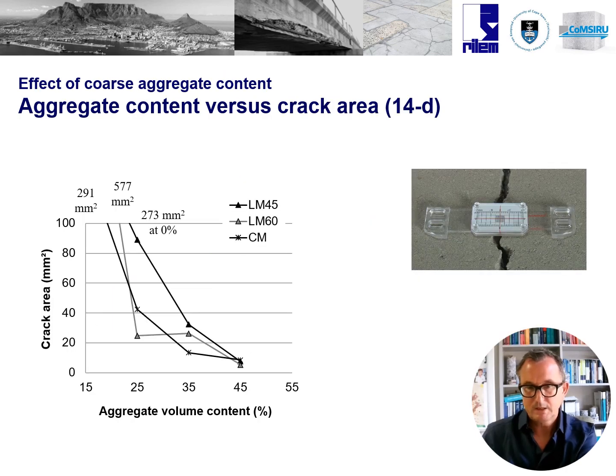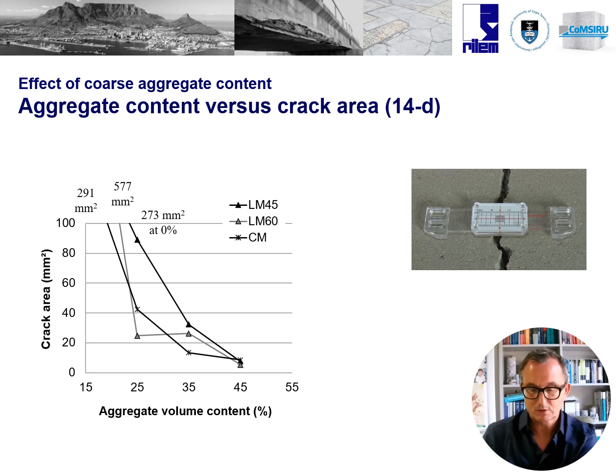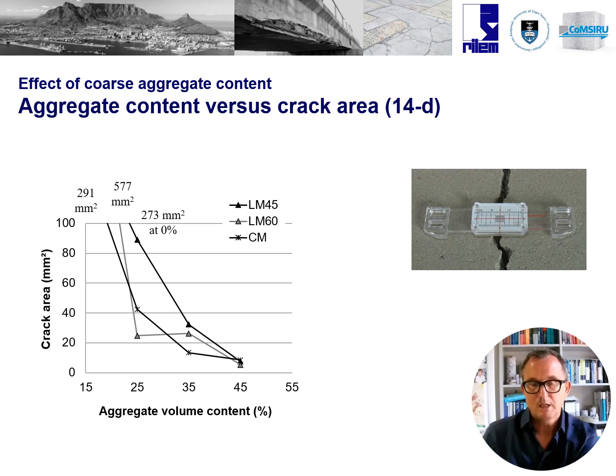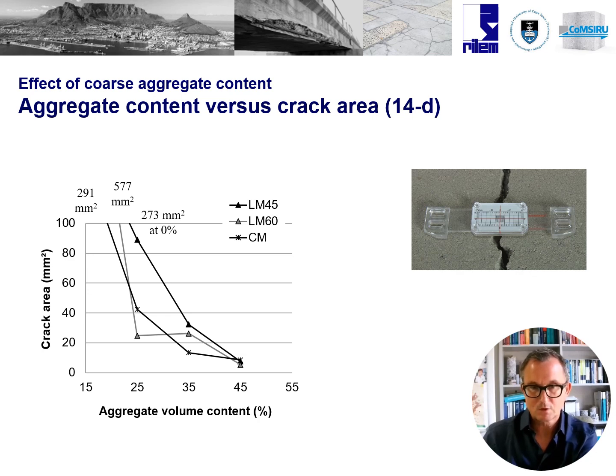Looking at the effect of aggregate content on the crack area — which is simply the crack length times the average crack width — there is again a drastic improvement in performance as the aggregate content increases, with much lower crack areas at higher aggregate contents.